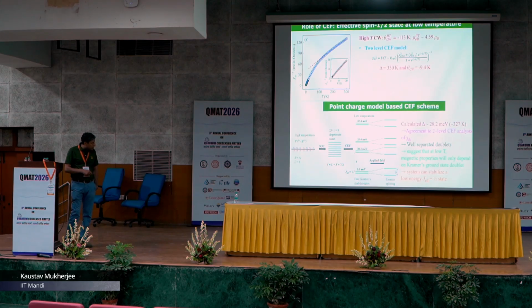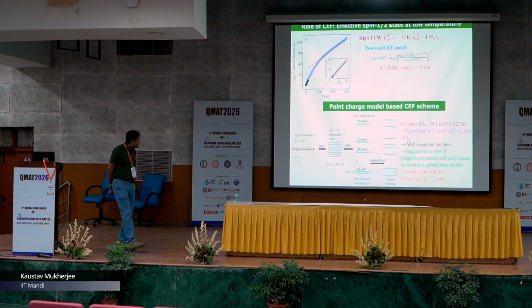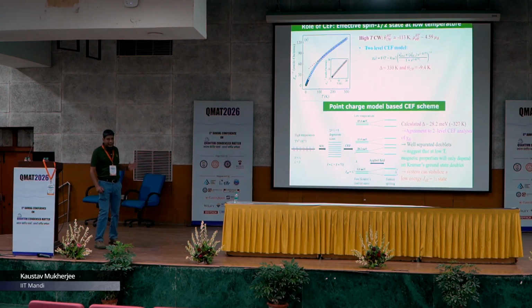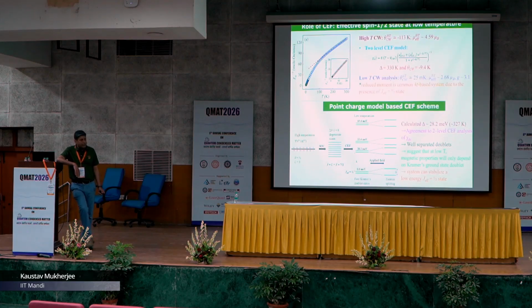So, this suggests that the low temperature magnetic properties of this system will depend only on the Kramers ground state doublet, and this system can stabilize a low energy J effective half state. Now, below 20 K we tried to fit the susceptibility data again with the Curie-Weiss law, and what we found is that the effective moment has a reduced value. However, we saw in the literature that this reduced moment is common in other 4f based systems due to the presence of the J effective half state, and from here the Landé g value was found to be around 3.1.